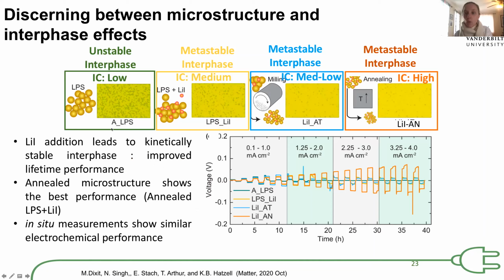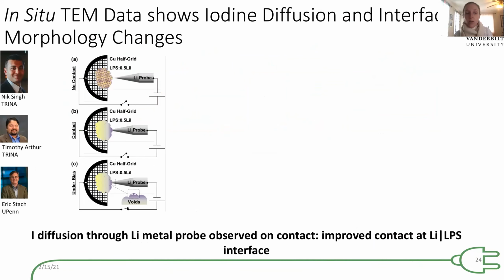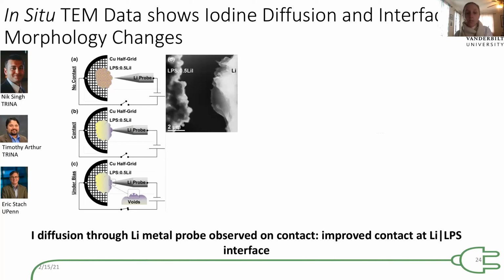To look at what was playing a role in transport at these interfaces, we collaborated with Toyota Research in North America, as well as the University of Pennsylvania, to do some in-situ TEM experiments where we can take a lithium metal probe and put it on our solid electrolyte and pull lithium out of the solid electrolyte or move lithium from the lithium metal probe to the solid electrolyte. So we can observe these interactions at a very, very local scale. This is just a TEM image of the lithium probe and the solid electrolyte.